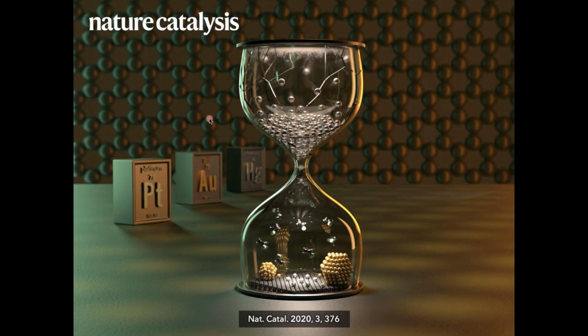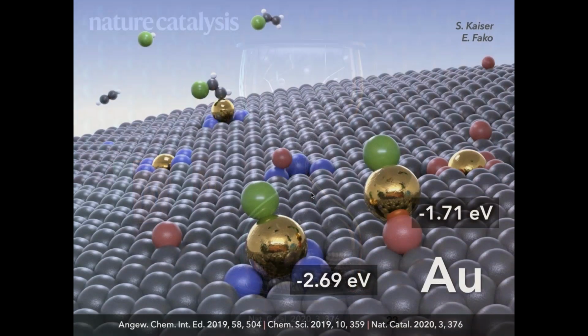And so we very recently studied, you can see here, noble metal catalysts based on single atoms in order to attempt this transition. It is well known from the work of Hutchings that gold, and gold single atoms in particular, are excellent materials. What you can see here is a gold single atom coordinated to an oxygen group of carbon, and what you see on the left is the same gold coordinated to a pyridinic nitrogen site on nitrogen-doped carbon. And what you see here is the energy of stabilization, 1.71 and 2.69 electron volts. So nitrogen helps bind the gold strongly.